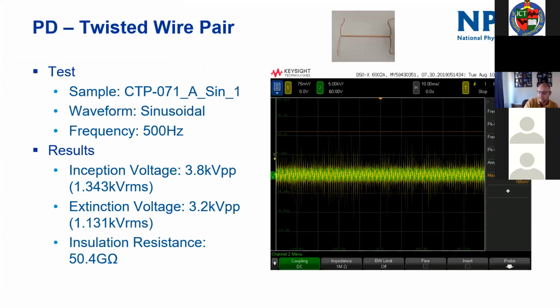So this shows PD within a simple twisted wire pair. This is a sinusoidal 500 hertz signal. That's the green signal. These graphs are not brilliant for display, but they're nice colors. But essentially, we're seeing an inception voltage there. The PD is the yellow signal in the background, and you can see these spikes occurring pretty much twice every cycle, as you go up through the sine wave and then back down through it. They occur somewhere around just under 4 kV peak to peak, which is about 1300 volts RMS with this particular sample.